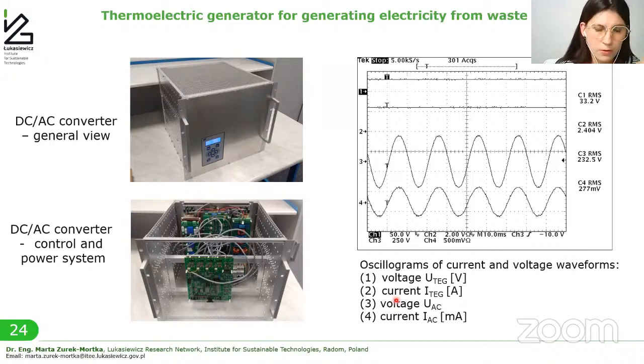The method consists in forced changes in the operating current of thermoelectric generators and the observation of power changes. The current changes should be continued in the same direction, increase or decrease, if the change increases the power. However, if the power decreases, the direction of changes in the work current should also be changed. So if the current was increased, start reducing it, and when it was reduced, start to increase it until the maximum power point is reached.